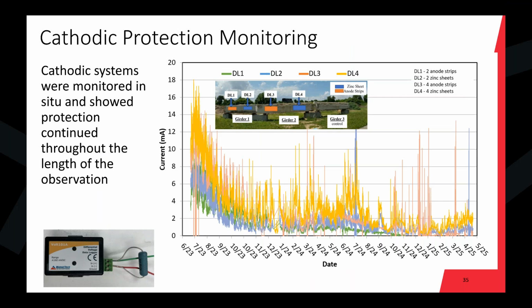And the way to think about the current is these are the electrons that we're getting from the steel that are going to the zinc that are not corroding the steel. So every electron that we're measuring here would have corroded the steel. And what you're seeing in the first 4 months or so is very much expected because we had so much exposed steel, a passivation of all those strands that had been cracked open on the sides. But by around October, November of that first year, we had reached a bit of a steady state, which means that the system is just working.